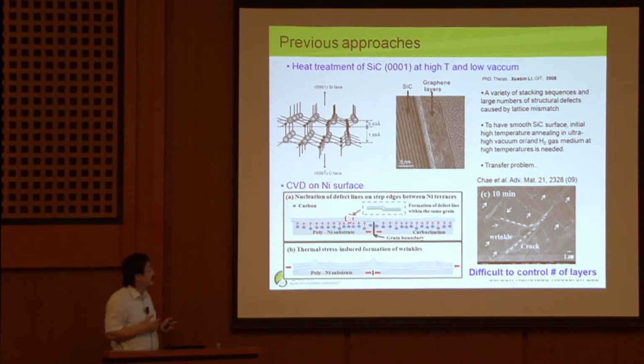We also did the same thing, and we were able to get graphene, large area graphene. But the problem is, again, the uniformity. From point to point, we get single layer, we get double layer, we get triple layer, but it's not uniform. We cannot control it. It's very difficult to control. There is a reason why you cannot control it.